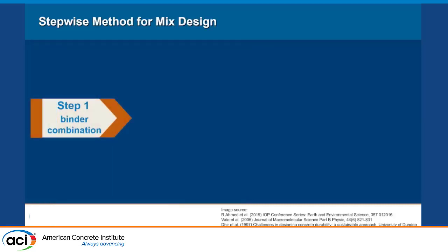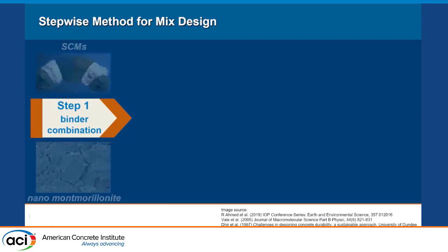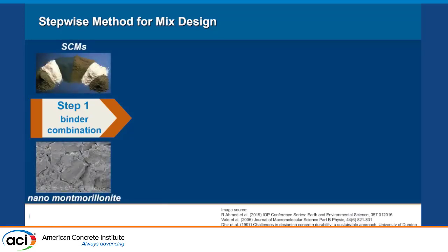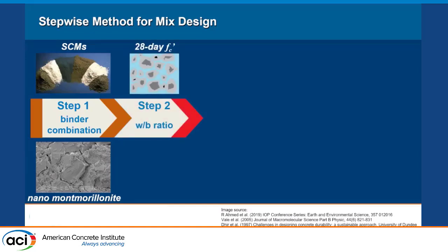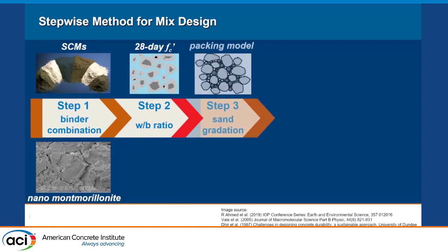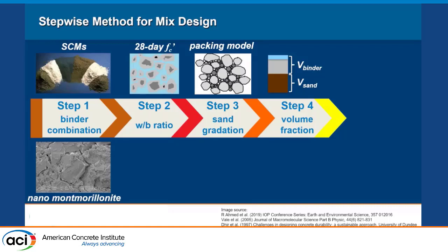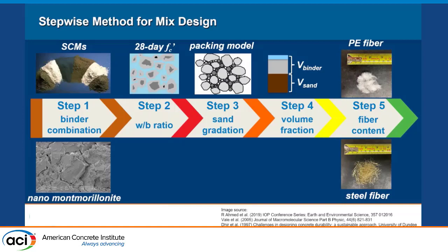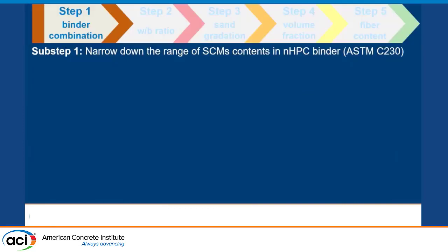So we employed a stepwise method for our mix design. The first step is to determine the binder combination, not only with the incorporation of supplementary cementitious materials, but also the nano-montmorillonite, also known as nano-clay. Then we move on to determine the water-to-binder ratio by the 28-day compressive strength of the paste. Then we will optimize the sand gradation of the mixture by employing a packing model. After that, we will determine the volume fraction of the binder phase and the sand phase. Finally, we will determine the fiber content of our mixture.